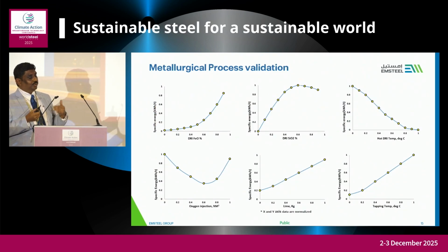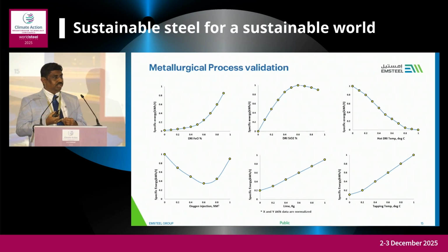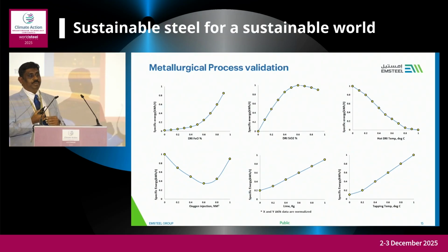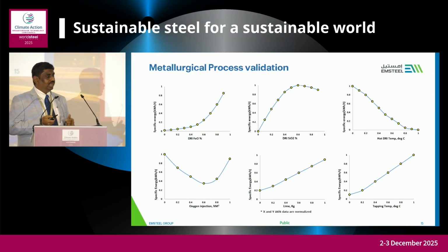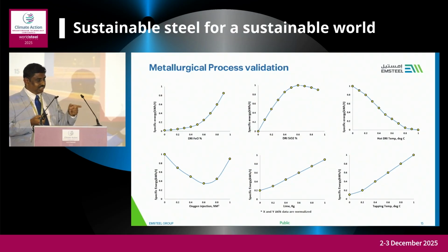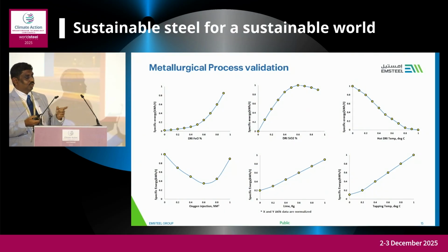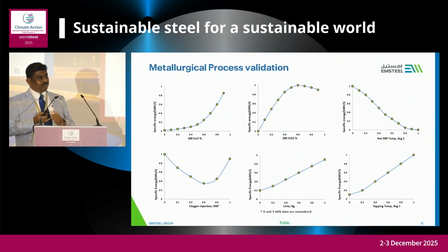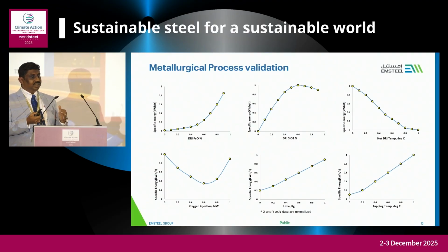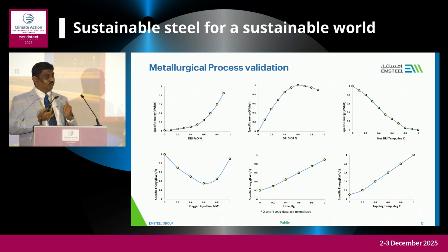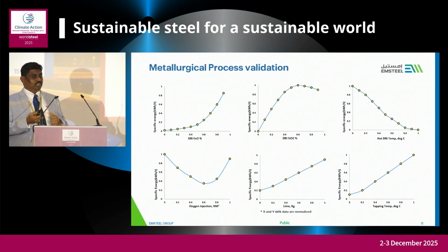Then after predicting with the model, we have done a correlation coefficient plot, which is a sensitivity analysis. What does this mean? We fix the other parameters and vary one parameter, changing the energy. If you see DRI FeO, which has an impact, because these plots are normalized on both axes, if DRI FeO is increasing, your energy is increasing. Similarly, if DRI silica content increases, your energy increases. If hot DRI temperature increases, your energy decreases. So we match the model result with the physical phenomenon of the process to validate it.